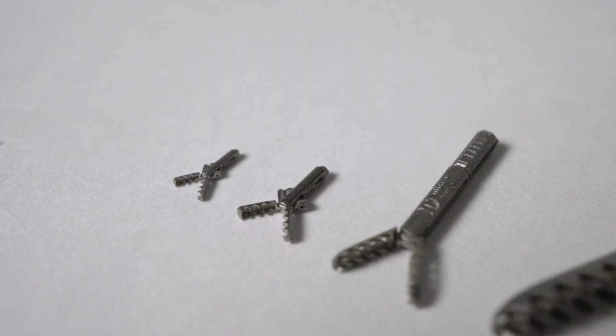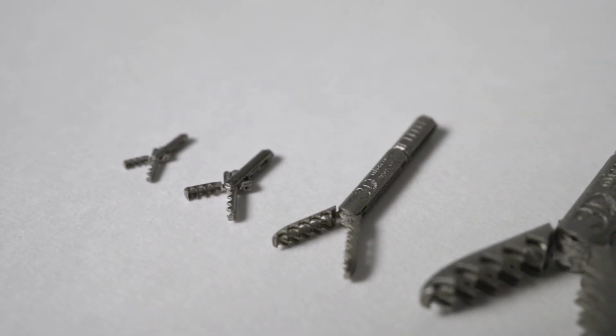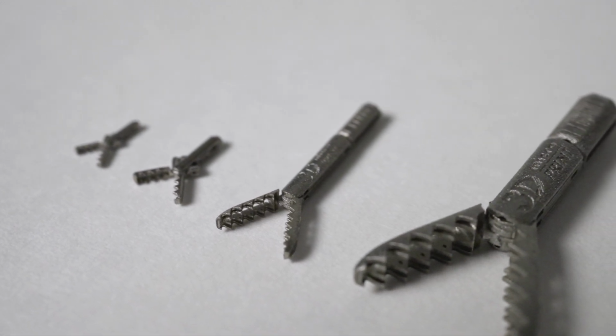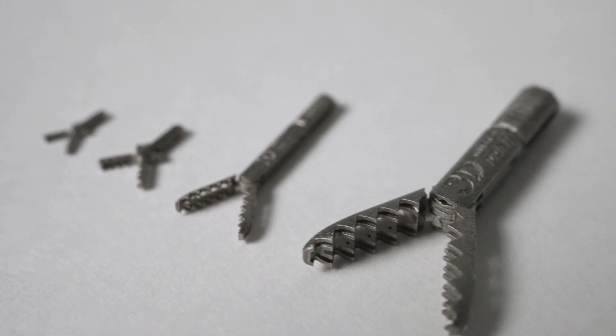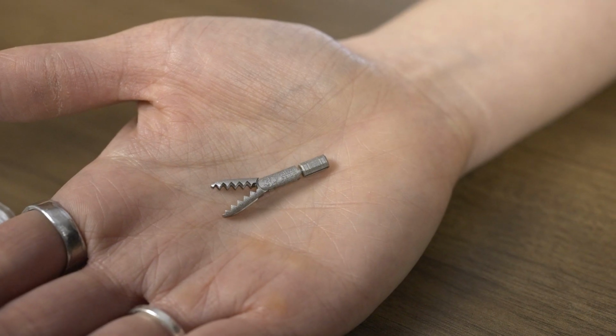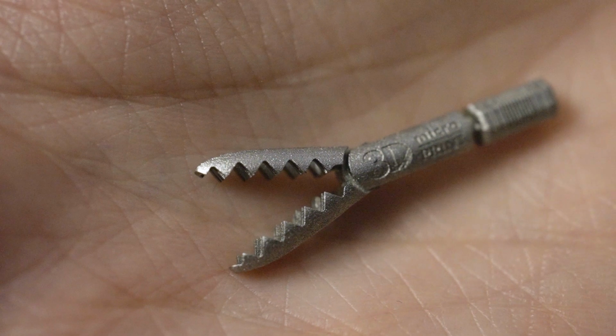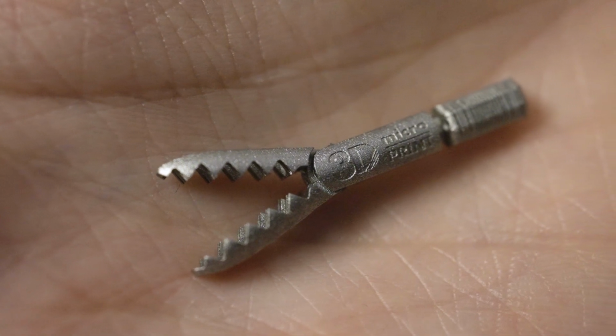So powder bed size usually is somewhere about 5 micron, but we also can go down to 1 micron if we get a powder for it, which is in a Z dimension. And in XY dimension, we are on a single build plate or for single pieces starting with 5 micron in the first step, or in the first centimeter in the square, and then going out to the edges of the building platform, we can guarantee a detail size of less than 25 micron. There's another advantage of this process that comes from the powder itself.